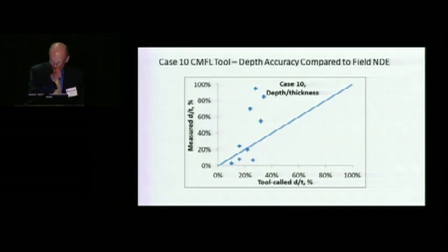Here was a case where a circumferential magnetic flux leakage tool in which the NDE measurements, again, were saying there's some defects a lot deeper than the tool is calling. But again, because of the particular circumstances of that pipeline, I think it's the NDE measurements that weren't believable in this case. But what it says is that if you run a tool, and the only thing you do is NDE, then it's hard for me to say that you can have a lot of confidence in that tool run if that's all you have.